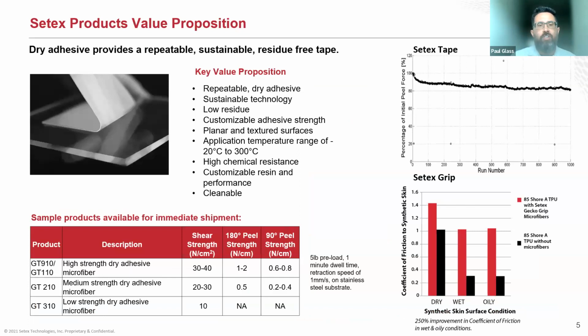Our products have very specific value propositions that address those needs in different markets. Our dry adhesives are repeatable, they're sustainable, they're reusable. So we have data here over 1,000 peel and unstick cycles, where we maintain about 80% of the original peel strength. And you contrast that to a conventional tape, tacky pressure sensitive adhesive that might work once or twice, but it's very quickly going to wear out. And so for a number of applications that go through a ton of tape, we can provide a huge value add, both in terms of reducing the cost of that application, as well as improving the sustainability. So there's a really significant move towards that.